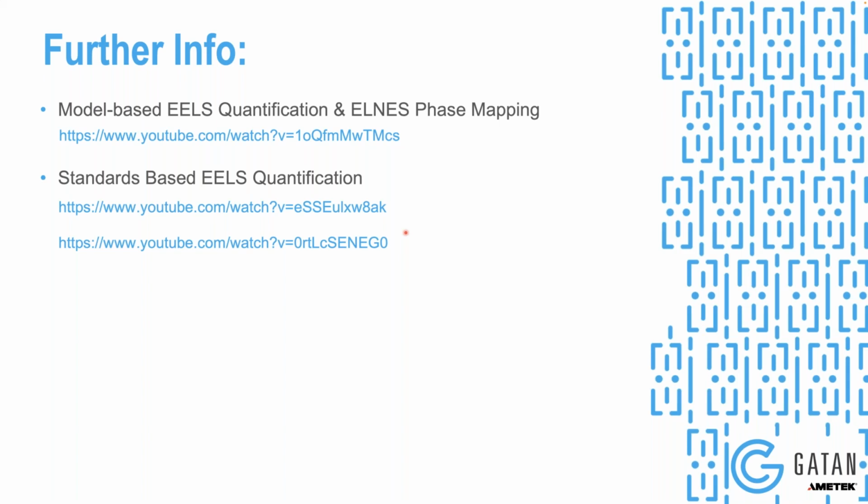Great. Actually, we just got a very related question. If you have an edge that's down at low energies and an edge at high energies, how do you do the mapping in that case, since one would be in the low loss spectrum image and the other one would be in the high loss spectrum image? So you could splice the data together. You can also map from the low loss spectrum. We just typically map from the high loss spectrum. But if you choose to map ionization edges that are in the low loss spectrum, that's possible, and the plural scattering correction will still be done,